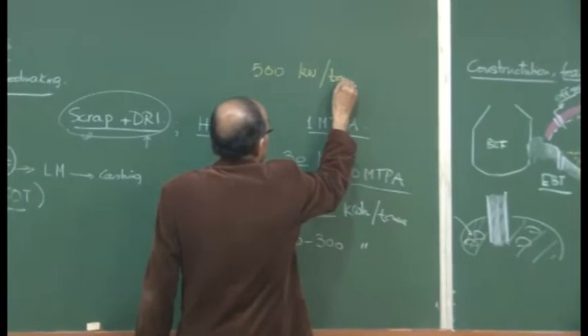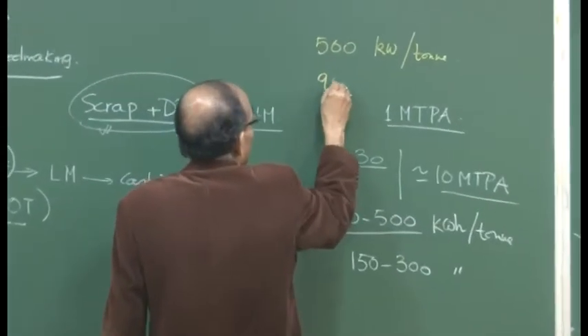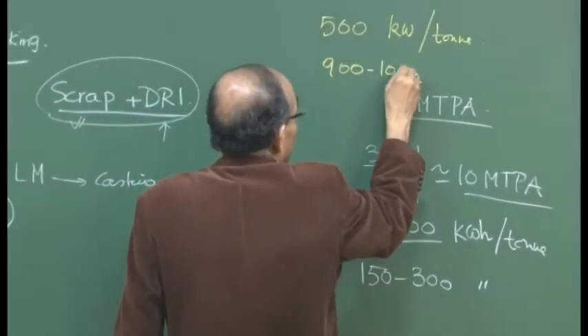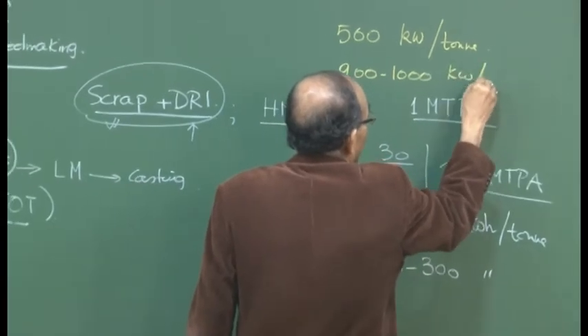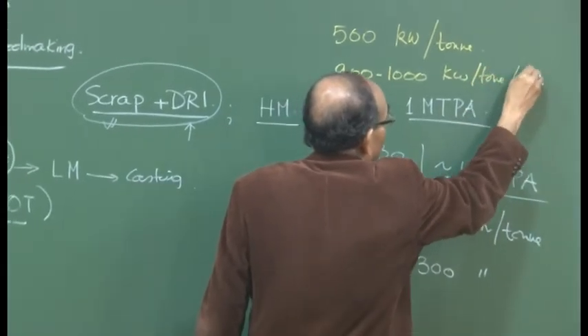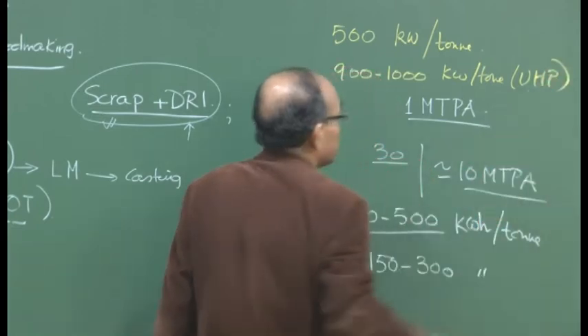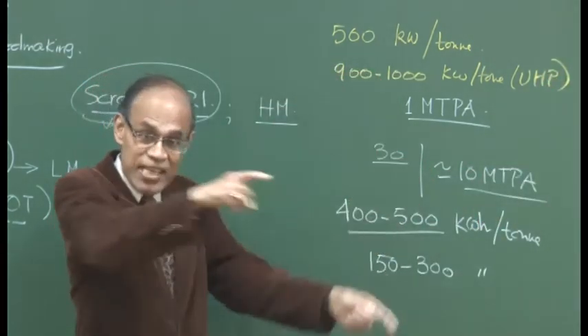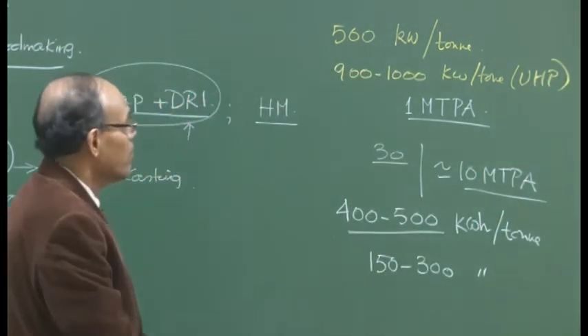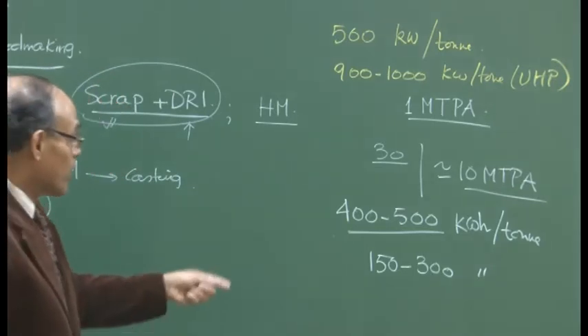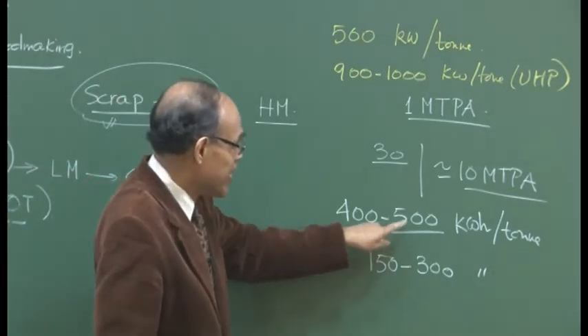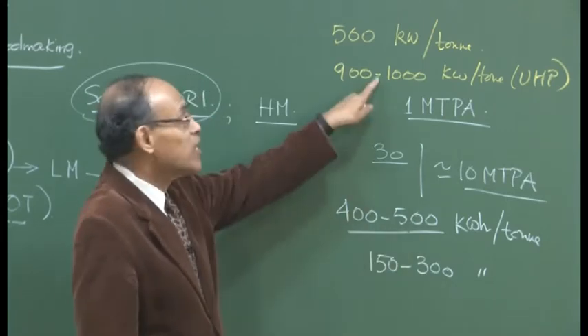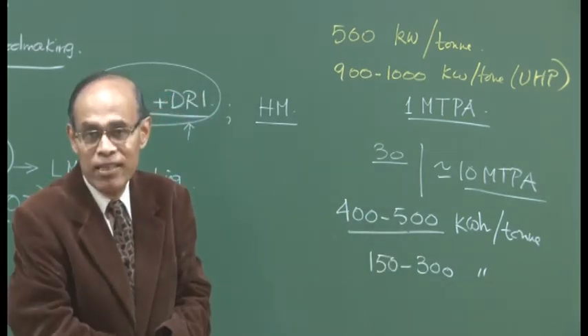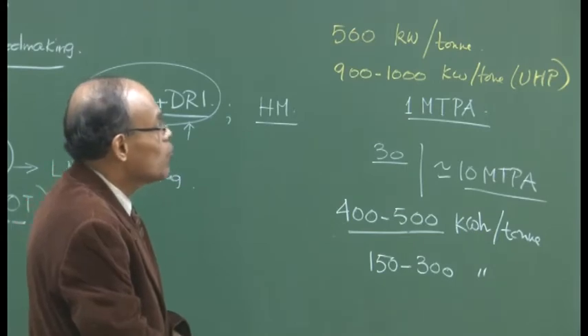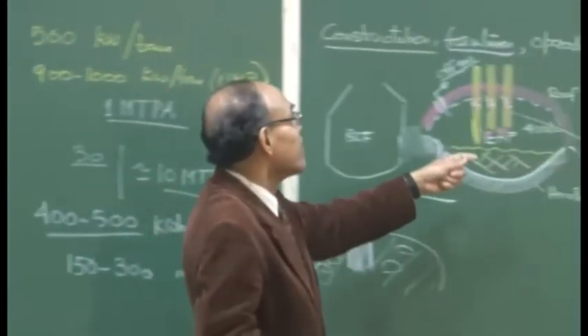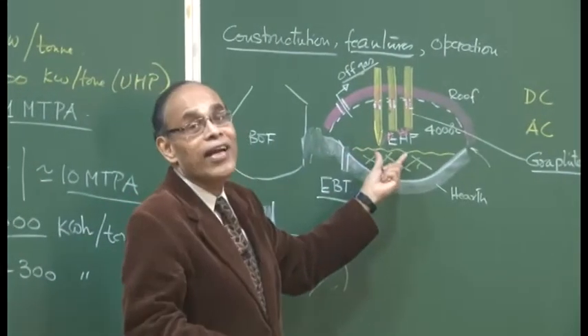It is a small furnace, and there are bigger furnaces where we can have 900 to 1000 kilowatt per ton. These are called ultra high power furnaces. You can imagine almost twice the rate at which the electric energy is being fed. So this amount of energy, which is the melting heat, can be supplied in this furnace at a very fast rate. Okay? And therefore, you can have huge electrical paraphernalia attached to an electric arc furnace,